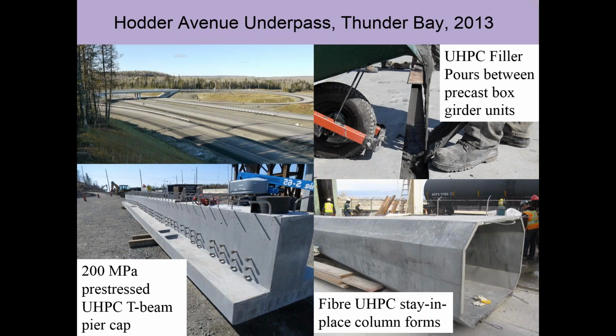And one example in Ontario where it was used is up near Thunder Bay on an overpass or an underpass. And they used pre-stressed ultra-high performance T-beam pile pier caps. And they made the column forms that are there. That's a column form out of ultra-high performance stay-in-place column forms. They erected them, they put the rebar inside and they put regular high performance concrete on the inside. So the outer part that's exposed to salt is ultra high performance. And then they use filler strips on the precast box units, filling up the pour strips with this ultra high performance material.